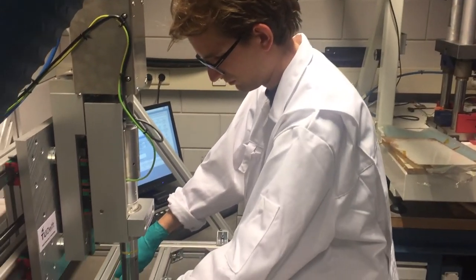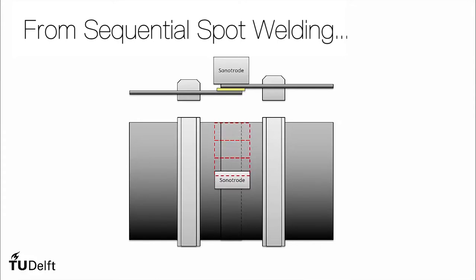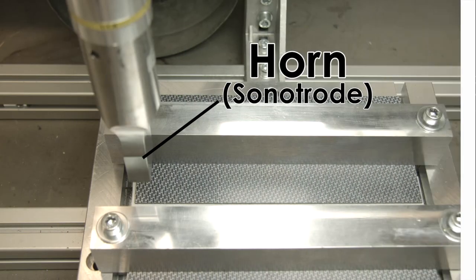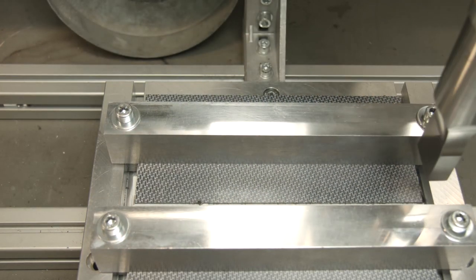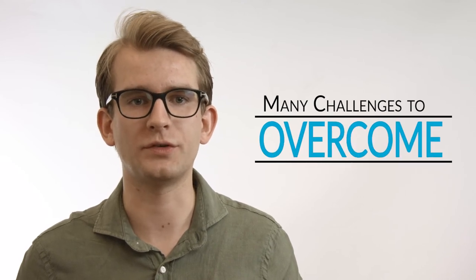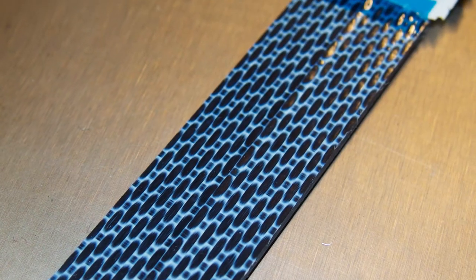This precisely is the topic of my PhD research. I'm investigating the challenges of transforming the spot welding process to a continuous process in advanced thermoplastic composite materials. My concept for this continuous process is to utilize a horn that moves over the weld line, applying high frequency vibrations, fusing the two parts together. Realizing this concept requires overcoming a number of challenges, including process control, thermal degradation, and part distortion.